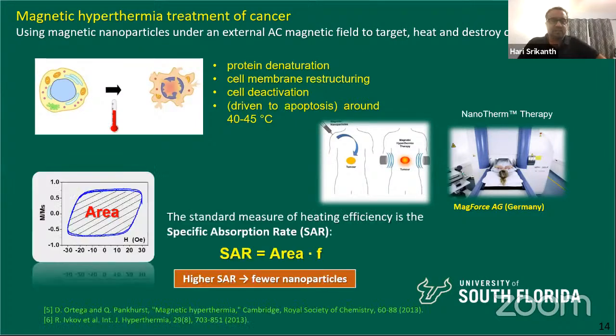So let's briefly talk about the physics of how this works. The answer is hysteresis loops. Why do you think I spent a lot of time explaining anisotropy and the shape of the magnetization curves? Because that's what we need. We need to maximize the hysteresis loop. Here's a strange looking hysteresis loop. This is M versus H. I know you've seen a lot of these cigar-shaped loops in ferromagnetic materials, probably in this conference.